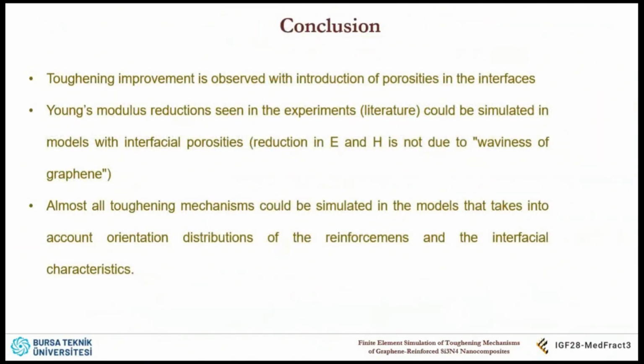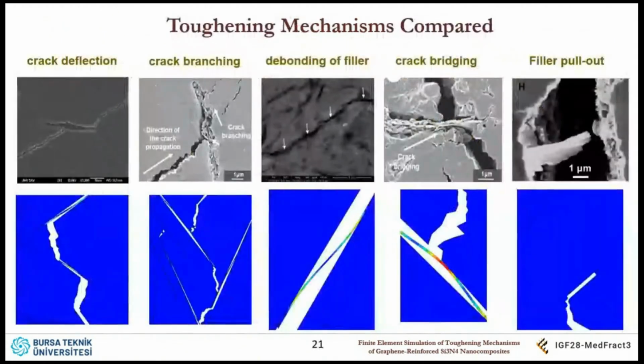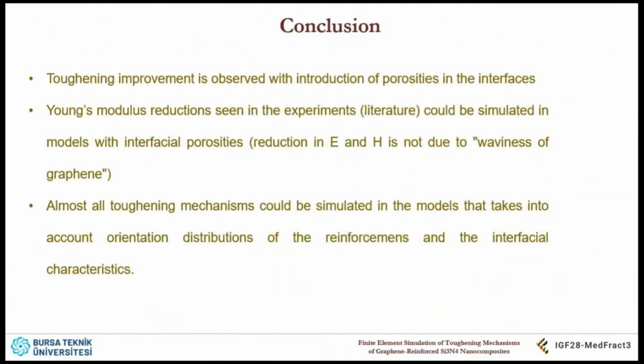But the experimental studies say that this reduction is due to the waviness of graphene. In fact, there is not much waviness in graphene. If you look at here, they are almost always flat. So this one, single graphene is wavy, that's correct. But these are multi-layer graphenes, and when many layers of graphene come together, they tend to be straighter. So this hypothesis given in the literature that reduction in Young's modulus and hardness is due to the waviness of graphene, I show that this is due to the porosities. Almost all toughening mechanisms I could simulate by taking into account the porosities and interfacial characteristics and also orientation distributions of graphene.